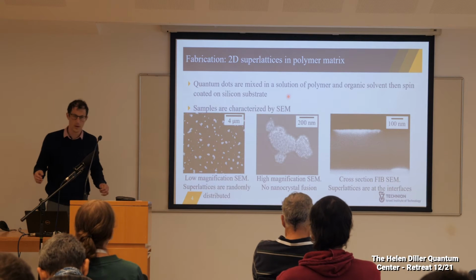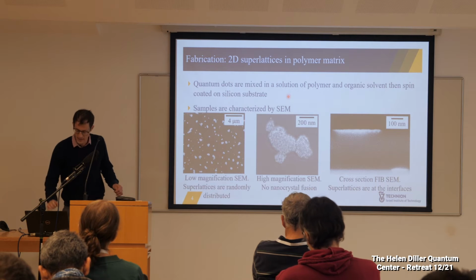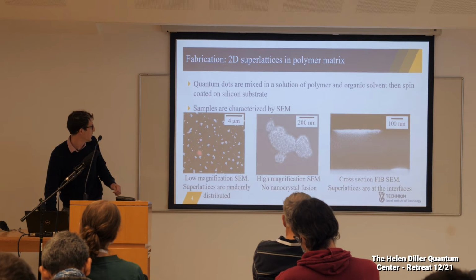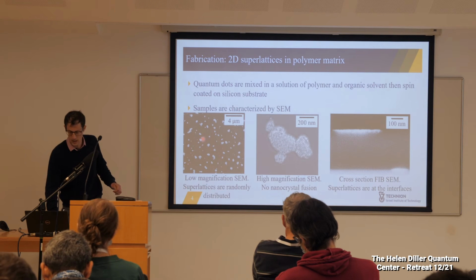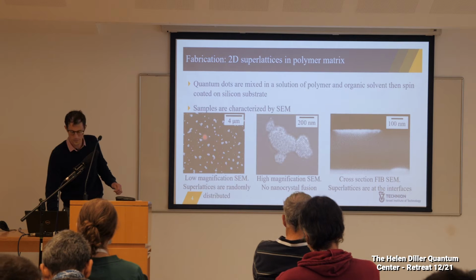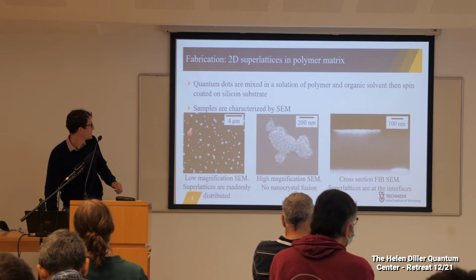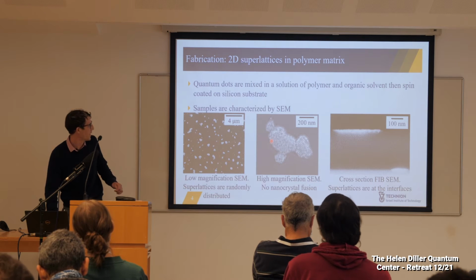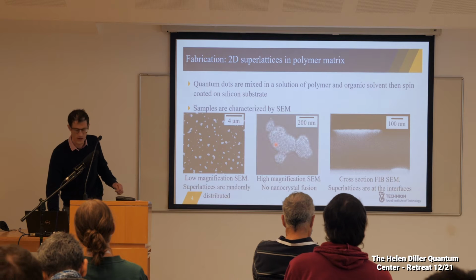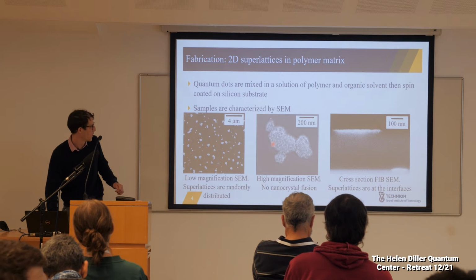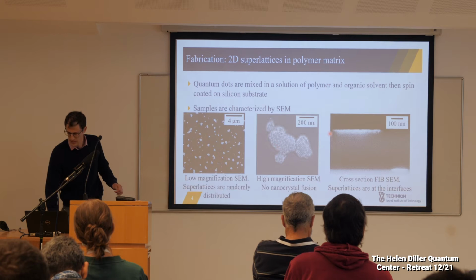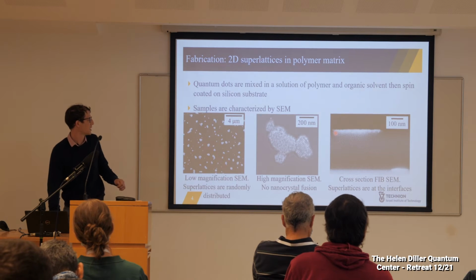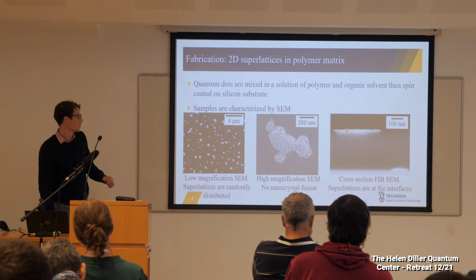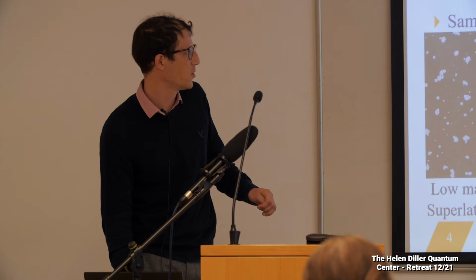We make a sample by taking these quantum dots, mixing them in polymer, and then spin coating it onto a substrate. Here you can see an SEM micrograph of our sample, where the black background is the polymer, and the white spots are the superlattices of quantum dots. If you go to higher magnification, you can see that these quantum dots are well defined, well separated. There is no fusing, and they are quite ordered. It happens for every superlattice here. It's very reproducible. And if we take a cross-section of the sample, we can see that these superlattices are not thicker than 2 quantum dots across. They form only at the top of the polymer or at the interface between the polymer and the substrate, as you can see here.